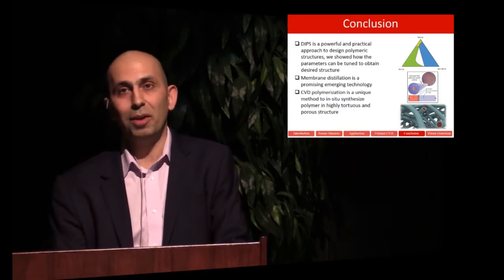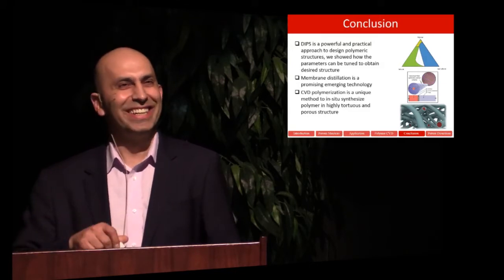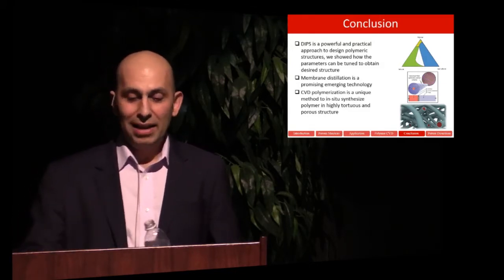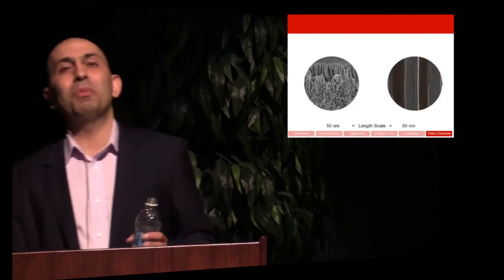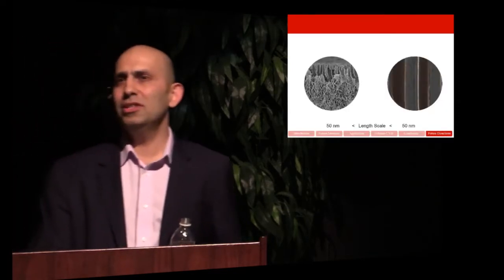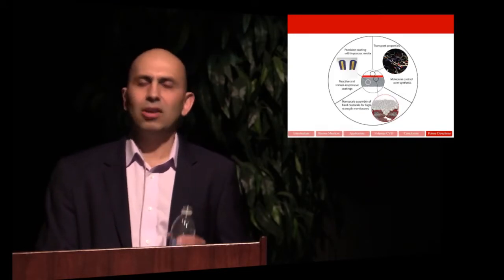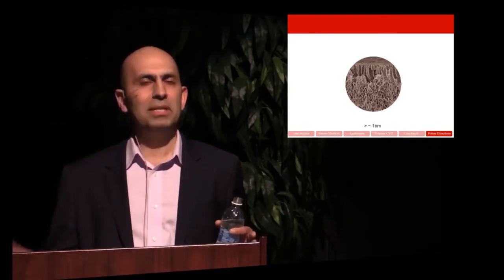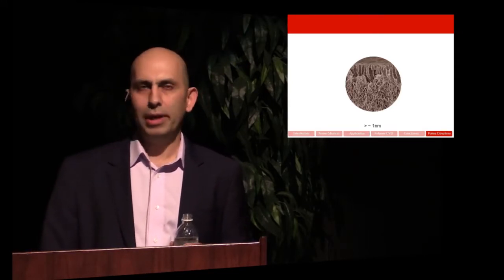It's getting to the time that I am losing the control of my voice. So with that, I would like to just tell you where I'm going with this. If you put these two together, you should be able to cover the whole range. Instead of 50 micrometers or less than 10 nanometers that we can achieve, we can create any structure and coat that with high precision. So we can have any surface we want with any property we want. Not only can we close the technology gap, we can also create new things, new materials, and metamaterials that can bring us new properties.